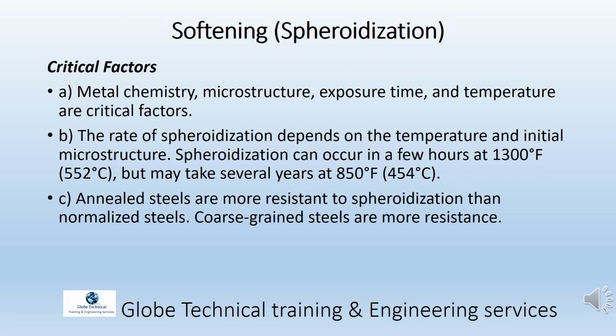A. Metal chemistry, microstructure, exposure time, and temperature are critical factors. B. The rate of spheroidization depends on the temperature and initial microstructure. Spheroidization can occur in a few hours at 1300 degrees Fahrenheit, 552 degrees Celsius, but may take several years at 850 degrees Fahrenheit, 454 degrees Celsius. C. Annealed steels are more resistant to spheroidization than normalized steels. Coarse-grained steels are more resistant.